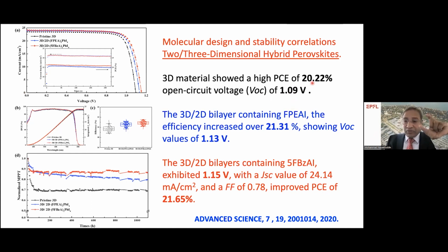we increase the efficiency from 20 to 21%, and the VOC from 1.09 to 1.13. And if you replace the monofluoro with pentafluoro, the VOC increased further from 1.09 to 1.15, and the power conversion efficiency increased to 21.65. But the small difference in the power conversion efficiency is very nice.